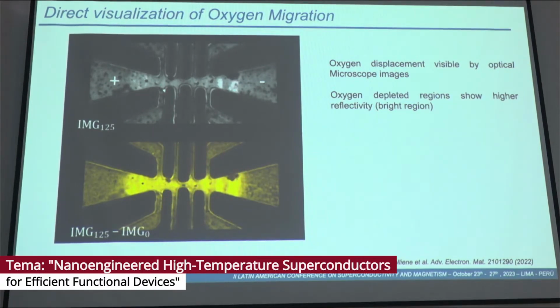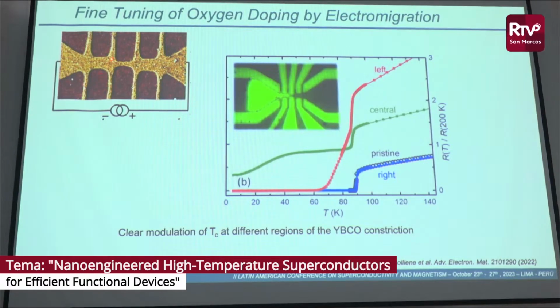So we are able to control the amount of oxygen that we have in the system by applying a current in the system by moving the oxygen ions, and change the contrast of the image because we change the resistance of the system. And by exploring different situations, one can tune the critical temperature of the system because since we changed the oxygen inside of the system, what we change is the critical current density.